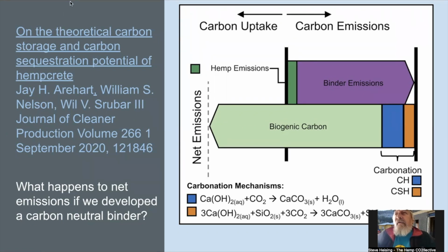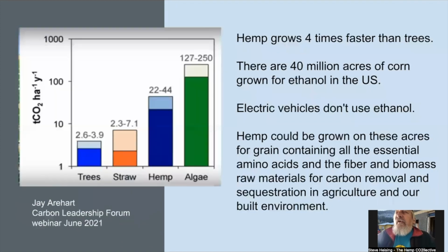And the byproducts are, you got biochar, which has a lot of uses. And the biochar, 5% biochar in any concrete has been shown to make it stronger. And I've calculated that if I could replace 5% of the cement and 5% of the sand in a 50-pound bag of Sakrete with 1 pound of biochar, I would reduce the carbon footprint of that concrete by 25%, which seems pretty simple to me. And that biochar is locked away forever, pretty much. And there's other uses for biochar, but what are you going to do?